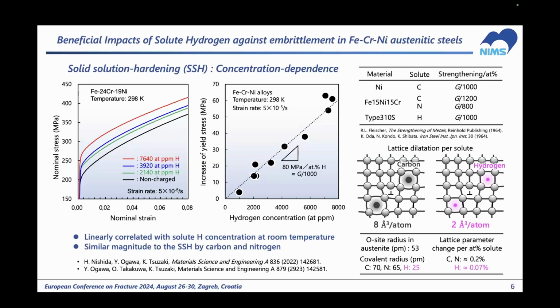As you know, solid solution hardening is a consequence of the interactions between crystal dislocations and the lattice dilatations around solute atoms. But hydrogen has just a small atomic diameter, and the lattice dilatation by the solution of hydrogen is too small to interact with dislocations. So this was quite surprising, and we are now studying what the mechanisms behind it are.